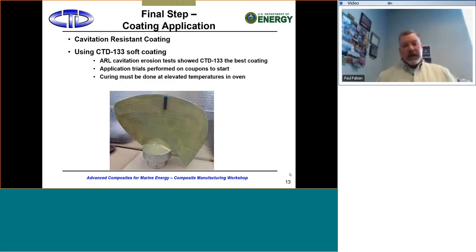And so then the last step really was to apply this cavitation-resistant coating. In this case, we were using one of our products called CTD-133. That's actually a pre-preg resin system, but we did a lot of testing in the first year looking at coatings and did a lot of cavitation erosion testing in the water tunnel at ARL, as well as other tests, and did a lot of different materials.